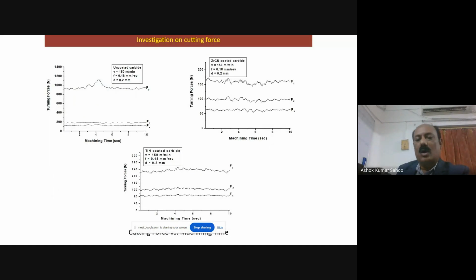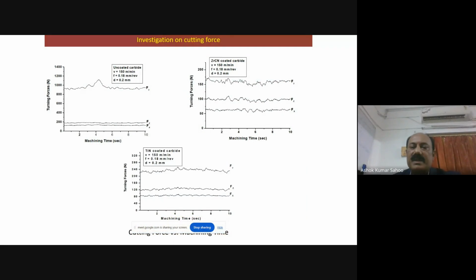And the progression of the cutting force in 3 directions, X, Y, Z, tangential cutting force, radial cutting force, and feed force, are also captured by the Kistler dynamometer, where you can observe the thrust force is maximum. That means the Fy force in the radial direction is maximum in comparison to the tangential cutting force and the feed force, because the depth of cut, 0.2 mm, is very small in comparison to the nose radius of 0.8 mm. So the cutting is taking place at the nose radius portion. That's why the radial thrust component of the cutting force is usually higher in hard machining, as is clearly observed in the graph.